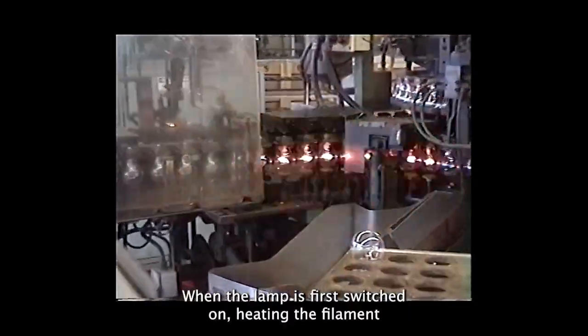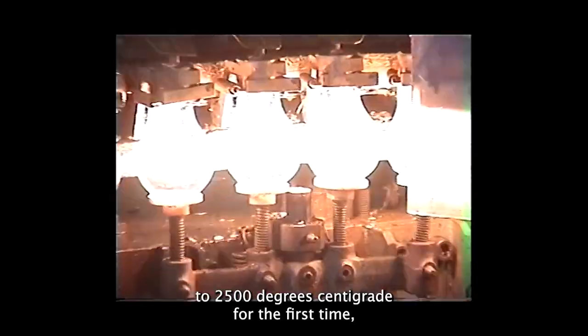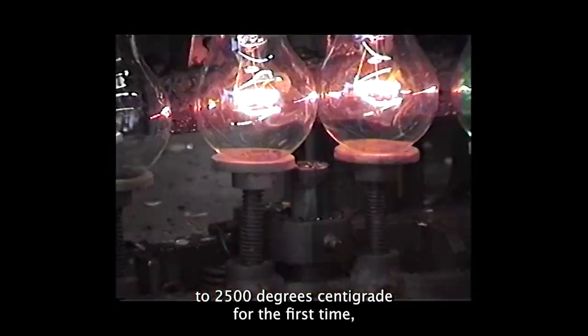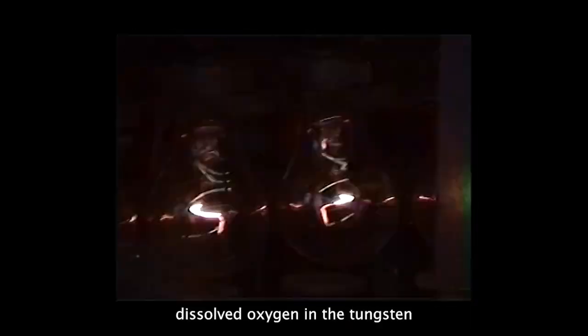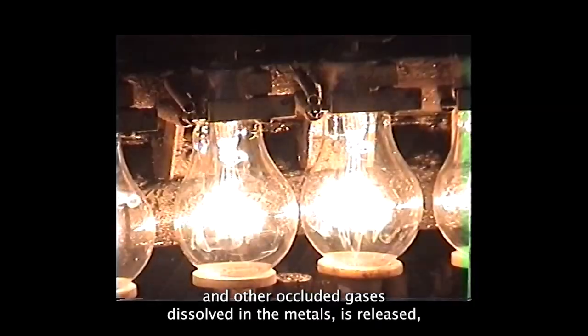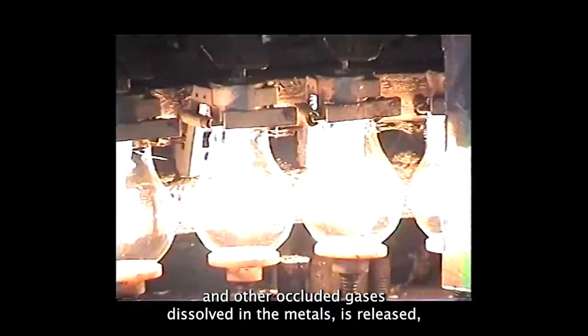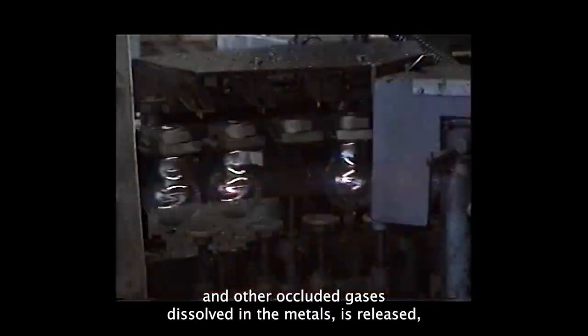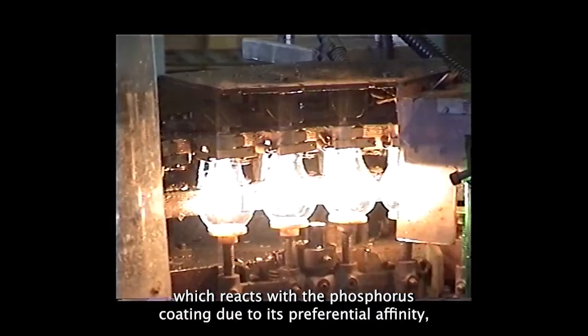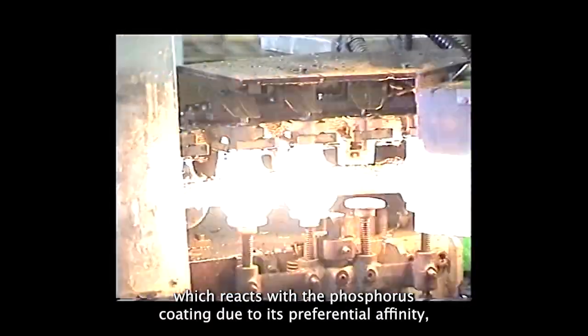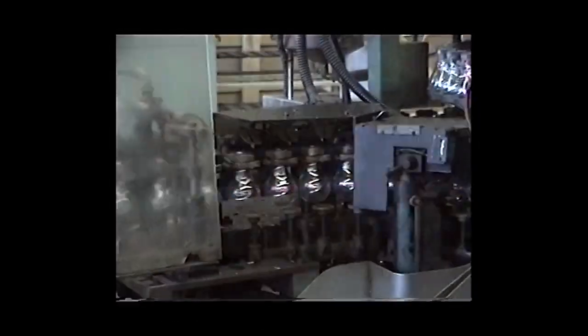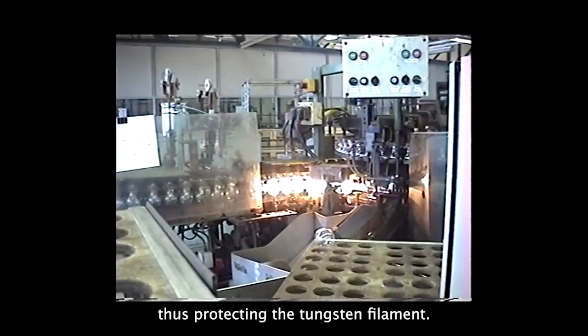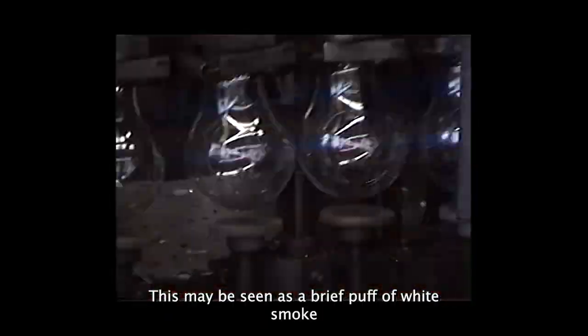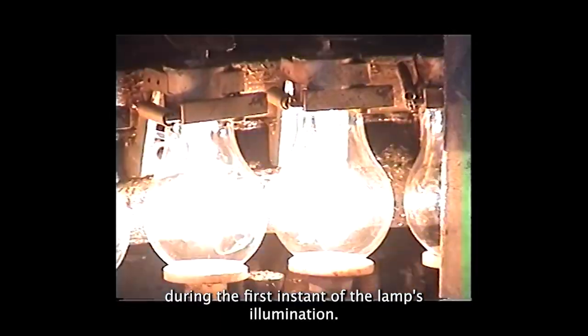When the lamp is first switched on, heating the filament to 2500 degrees centigrade for the first time, dissolved oxygen in the tungsten and other occluded gases dissolved in the metals is released, which reacts with the phosphorus coating due to its preferential affinity, thus protecting the tungsten filament. This may be seen as a brief puff of white smoke during the first instant of the lamp's illumination.